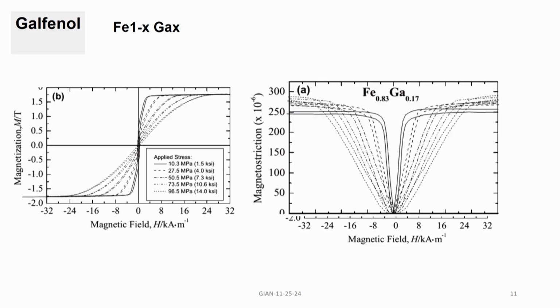Galfenol, even though it has iron and gallium, gallium is not a rare earth, it is not susceptible to oxidation, it has very high magnetostriction, as high as 250 parts per million, and we have used Galfenol also in many of our composites, but the properties such as magnetostriction depend on the amount of iron and gallium in the Galfenol. It changes with X.